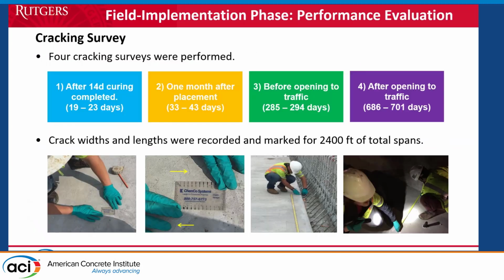And then what we did is we asked to survey the cracking at different stages. We wanted to confirm that what we're seeing in the lab, you can also see in the field. So we did the first fingerprints before opening it to traffic, after the curing, when they removed the curing. We did the mapping. We measured the crack width and the crack length. And we had an army of students do that. And we marked them, we colored them. And we did that more often.